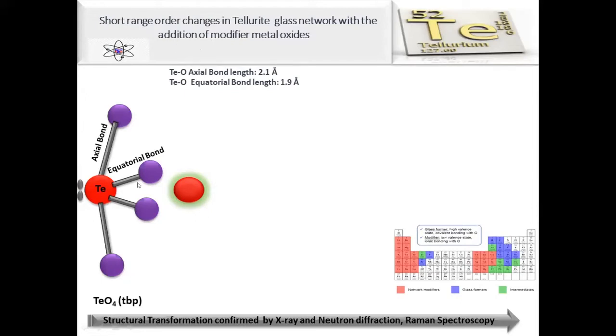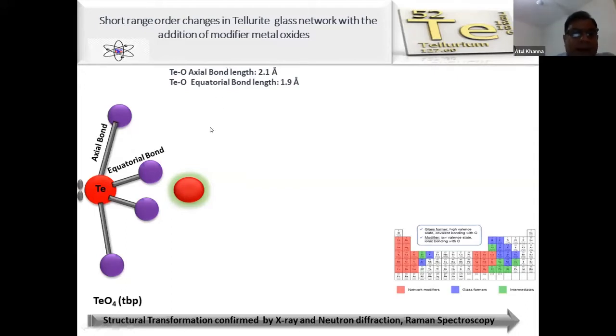And the structure of the tellurite glass consists of TeO4 units. In TeO4 units, each tellurium atom is bonded to 4 oxygens, and the tellurium atoms also have a lone pair of electrons. These electrons are not chemically bonded to any oxygen atom. They give rise to very large polarization of the material. And when you add some network modifiers like alkali ions or calcium ions or tungsten ions or silver ions or cupric ions, then these TeO4 units